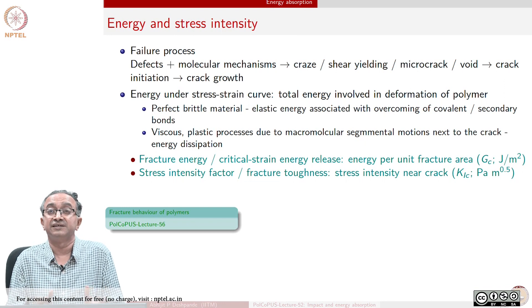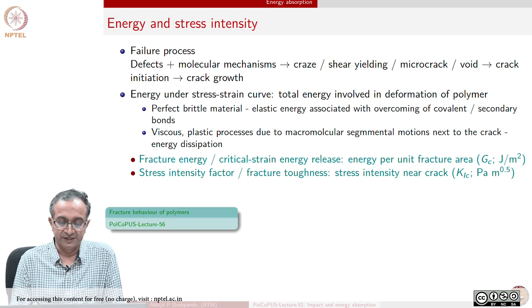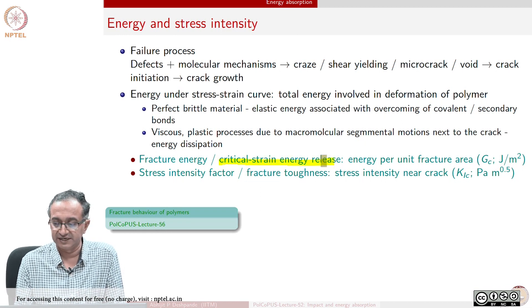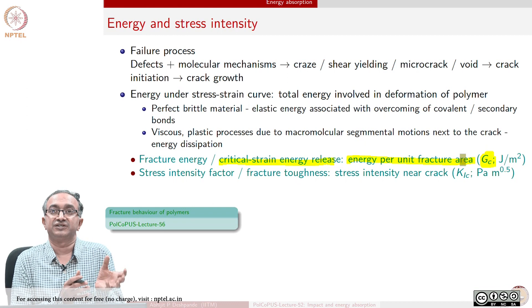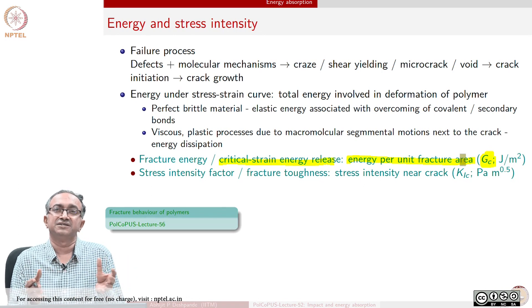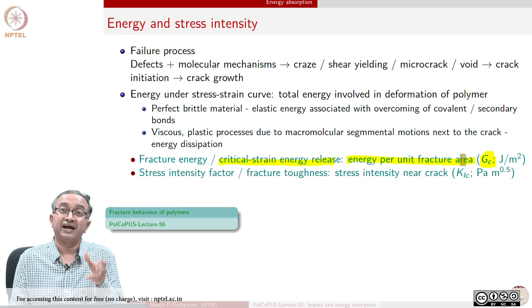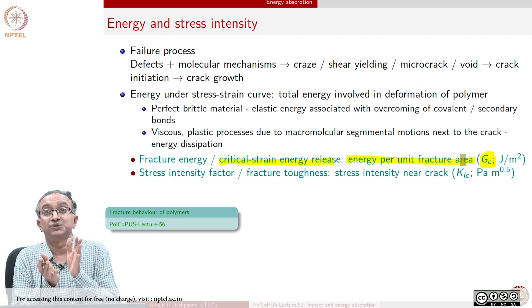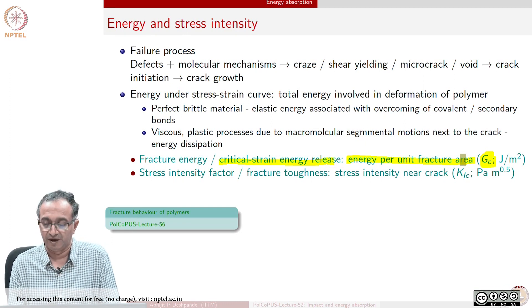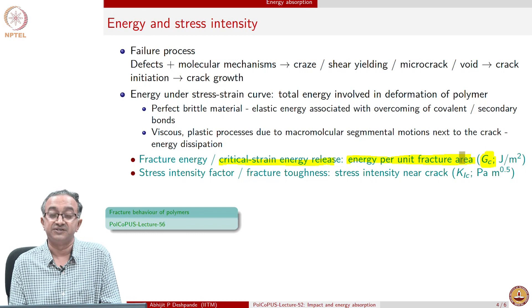Many fracture mechanics concepts were initially developed based on elastic materials, but have been extended to viscous and plastic materials. Near the crack, what happens is very different: an elastic material only stores energy, while a viscous-plastic material can dissipate energy and allow structural rearrangement of macromolecules. We can analyze fracture phenomena by looking at what is called the critical strain energy release rate — factor G — which is energy per unit fracture area, quantifying energy absorbed per unit area of the crack surface that is opening up.